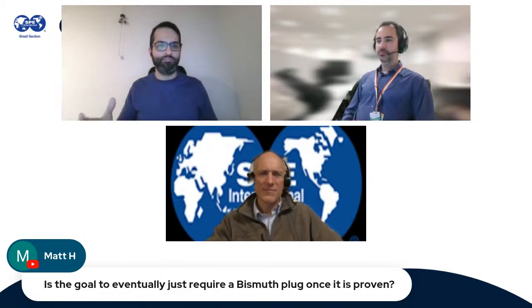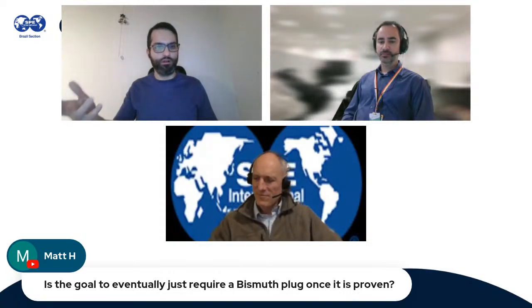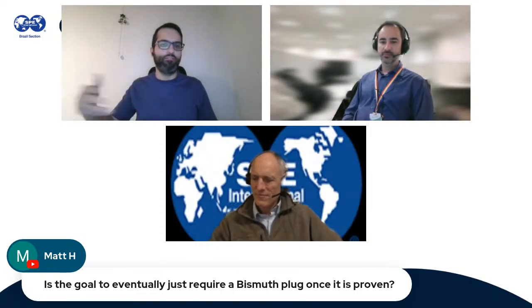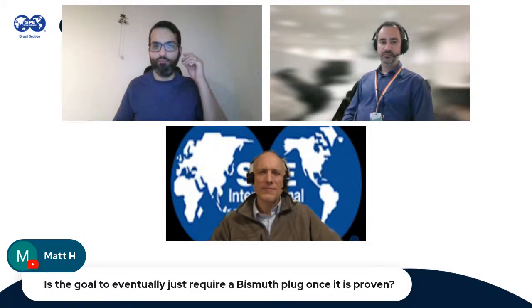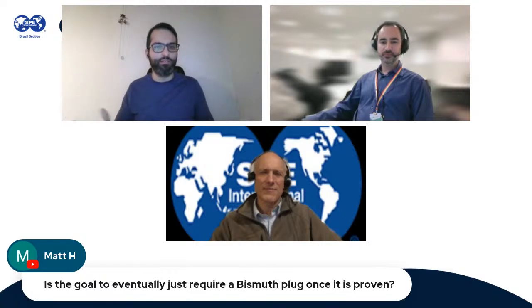So I don't really foresee a future where they're going to simply replace cement with another material. But instead, you might have very specialized cases where you have some poor cementing job, and then you want to put the bismuth plug in place to improve integrity. And then you have cases where you could use other alternative barrier materials as a way of creating further redundancy in terms of your barrier elements. But I don't see bismuth easily replacing cement, because I know there will be a lot of resistance from the industry itself in replacing a material that has been used for decades. But maybe you could give a perspective from Petrobras.